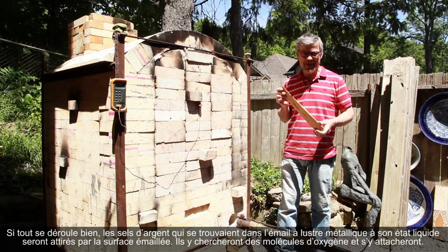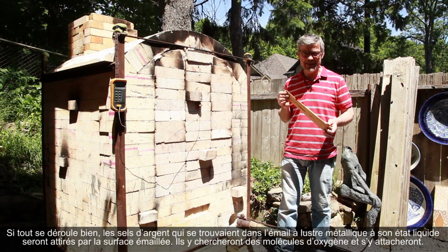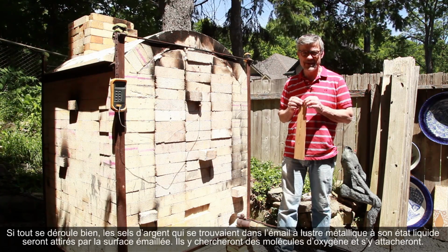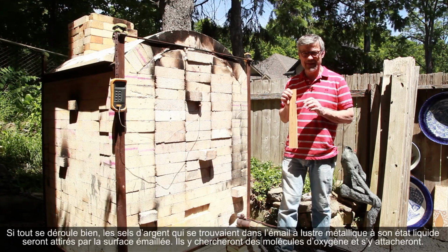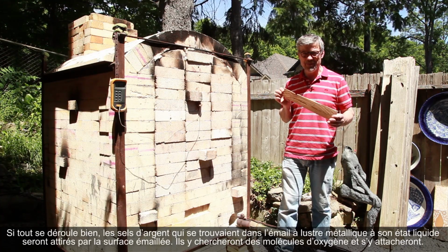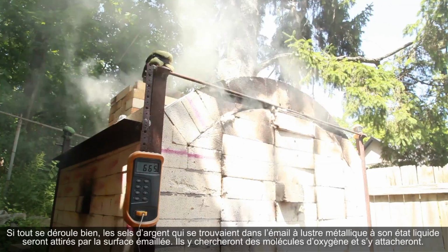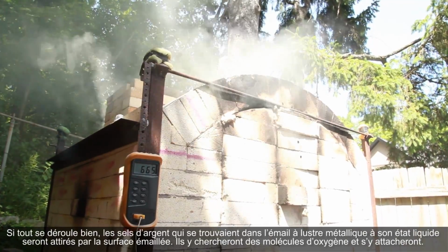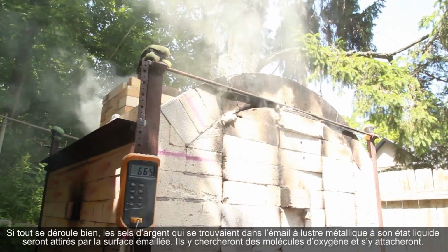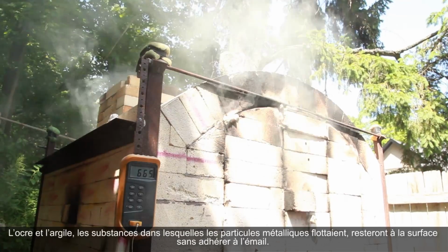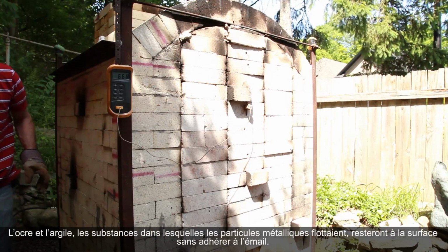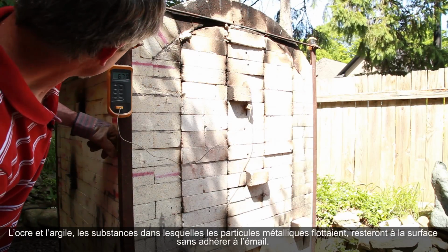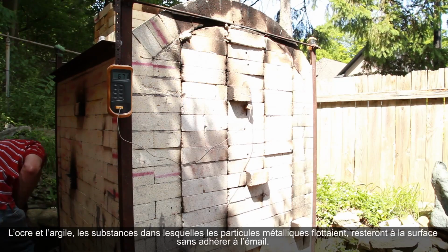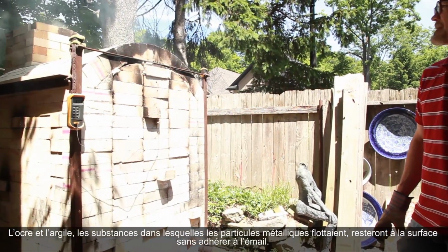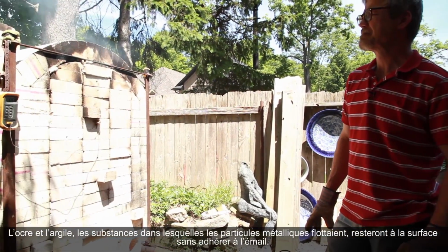And in that way, if everything works right, the silver salts that were in solution, in fluid, in the luster compound will be attracted to the glaze surface. They'll look for oxygen molecules there and actually will bind to the surface of the glaze. And the carrier, the ochre and the clay that all that was floating in, so I could brush with it, will stay up on the surface and not stick to the glaze. So that's the goal.